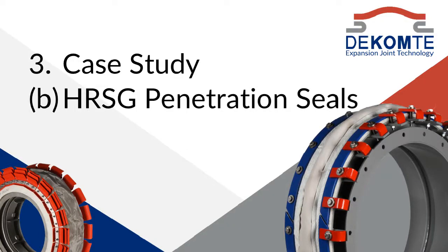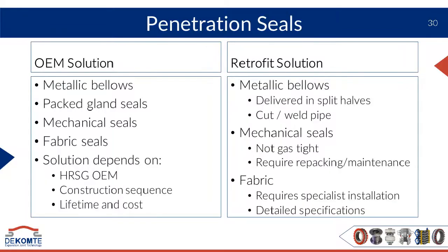The second case study I just want to then touch on is penetration seals. Penetration seals are the most prevalent expansion joint type in a combined cycle plant. Anything from 30 to 80 of these on the floor, roof and side walls of the HRSG. Every steam pipe that penetrates through the casing wall needs to be sealed to the casing wall itself. We're supplying OEM and retrofit solutions, and for the OEM, the main choices are metallic bellows, packing glands, mechanical seals, or fabric expansion joints. We only supply gas-tight solutions, so we only focus on fabric and metallic bellows, which we supply both as an OEM.